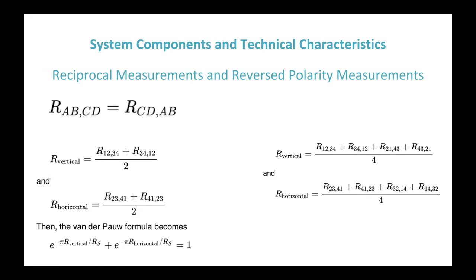For the reverse polarity measurements, a further improvement in the accuracy of the resistance values can be obtained by repeating the resistance measurements after switching the polarity of both the current source and the voltage measurement portion of the sample. Using the opposite direction, the values of resistance vertical and resistance horizontal can still be calculated as the average of the reverse polarity measurements. The benefit of doing this is that any offset voltage, such as the thermoelectric potential and the thermal effect, will be cancelled out. Combining this method with the reciprocal measurements gives the formulas for R vertical and R horizontal.